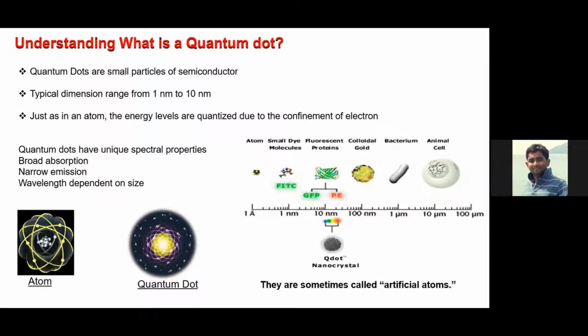But if you go to lead sulfide or lead selenide, the band gap is present in the mid-IR. So mid-IR means your particle size goes to a maximum of 12, 13, or 14 nanometers. That's why I say the typical dimension, for the maximum number of quantum dots, belongs to the range of 1 to 10 nanometers. And now, why is it called a quantum dot?